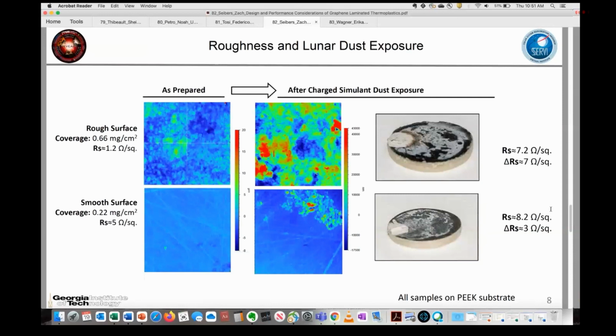I think this is important to note because we obviously want to make these samples as smooth as possible. It makes sense from a physics and material science perspective that that's going to be better at dealing with dust. However, as a design parameter, if you want to think about how to protect the suit or protect different materials, how porosity and roughness play a role in this lunar dust environment is very important. And I'll just note the change in sheet resistance. Both of these are still plenty conductive for a variety of applications, but the point here is that there's a big change in the sheet resistance.